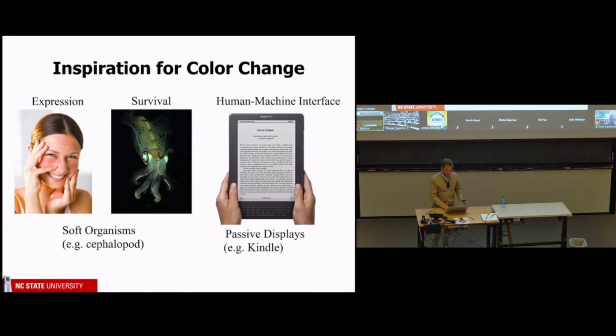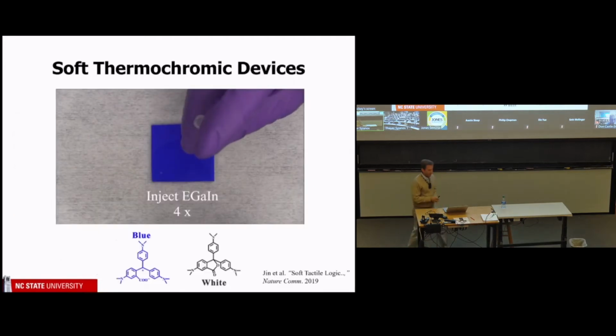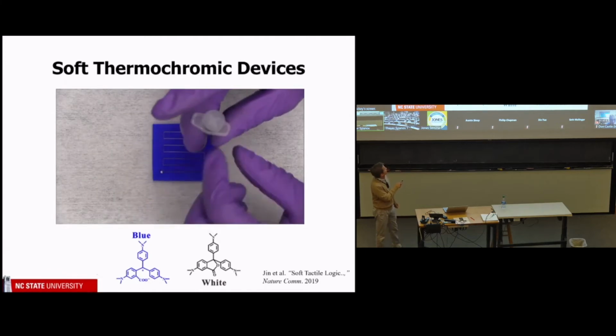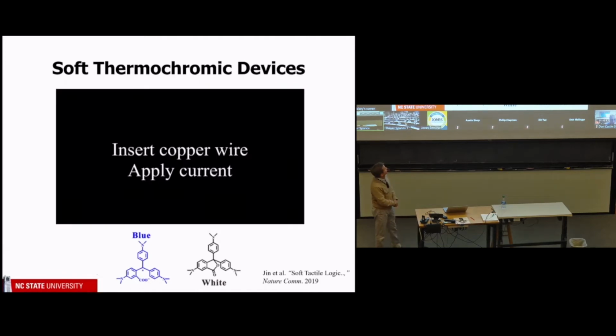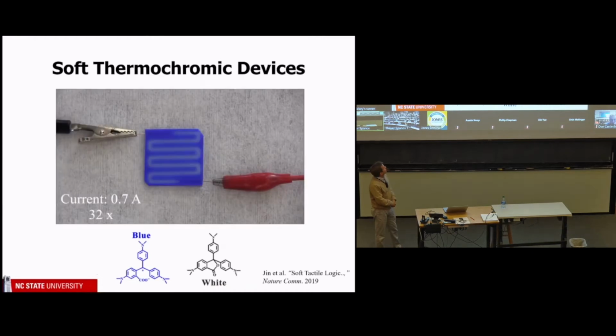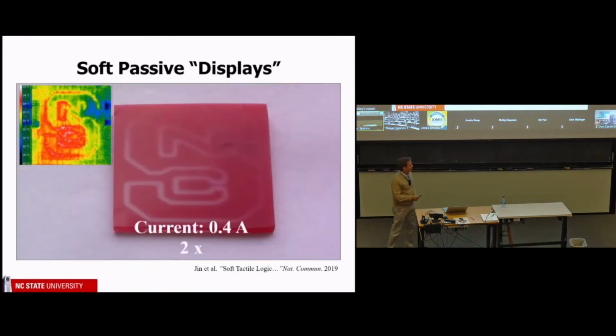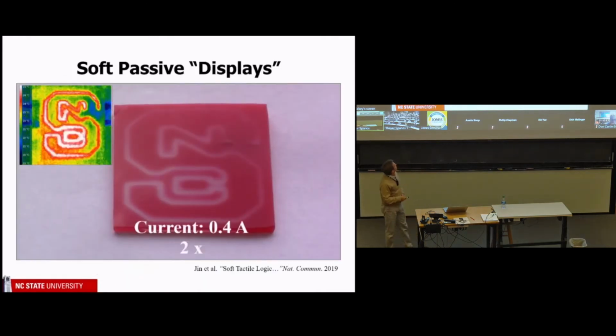So I had this visiting student named Yang, and he brought with him these pigments. This is a pigment that starts out blue, so we just mix it in with the silicone, we inject liquid metal, and then we run current through it, and that causes Joule heating, and when this stuff gets warm, it changes color. So, okay, kind of obvious, but looks nice. And there's different pigments. This is a red pigment, and we pattern the liquid metal to make it look like the NC State logo, so that's kind of cool. And if you look with a thermal camera, you can see indeed this is just a thermal effect.